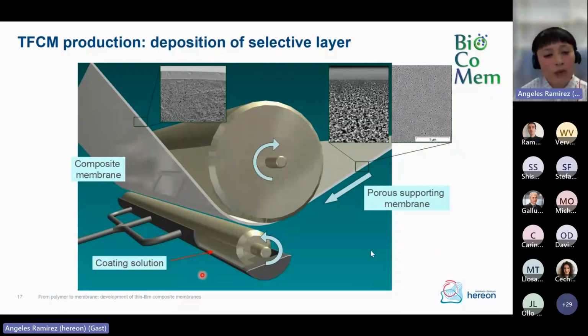And now, when we already have the gutter layer, we can proceed to deposit our selective layer. And this we do by means of a modified dip coating method at our institute, which is called the meniscus coating method. And this is done in a pilot scale machine comprising a 2-roller system, as you can see here. So we place the coating solution in this reservoir, and then we roll the porous support on top of it.